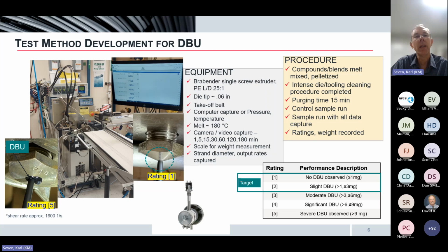In order to evaluate the die buildup itself, we developed a rating scale of performance, basically 1 through 5, with 1 being no buildup, like I show here, versus a 5, which would be severe buildup. Throughout this test period, we also captured some other parameters, such as output rates, strand diameter, and so forth, to ultimately evaluate processing aid performance.